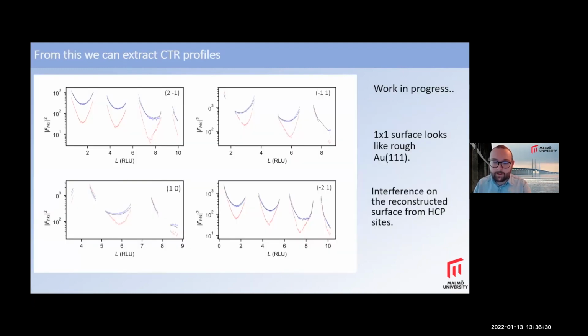You can extract the profile of these CTRs. I've done a sort of a quick fit of these. It needs a little bit more work, but basically at the high potential, when we've lifted the reconstruction, in this case, it looks like a very rough gold surface. So that's why the model's not perfect. I have to play around with some roughness models for this. And then when you have the reconstruction, you get this strong interference effect. And you can see that the intensity dips between the Bragg peaks quite dramatically.